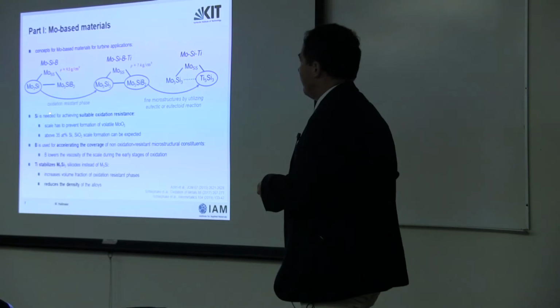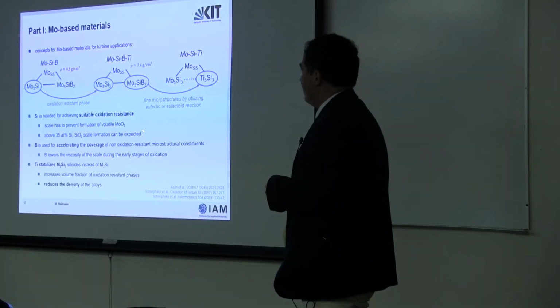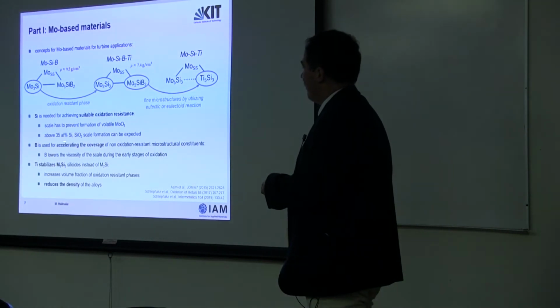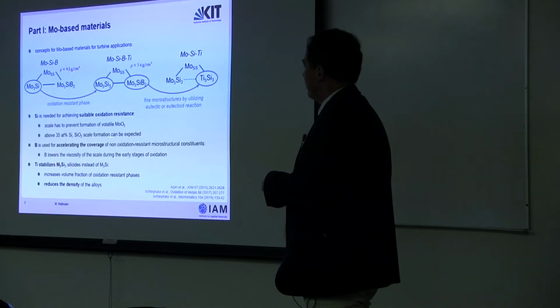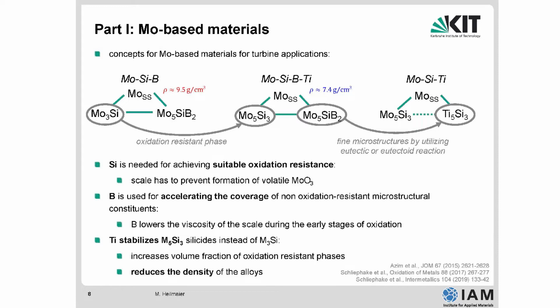You need silicon to avoid this, but you need a high amount of silicon, above 35 atomic % silicon, to get a silica scale formation here, which is a lot. Yeah? So we try to avoid this because this material becomes extremely brittle. What else could you do? You could add other elements to alleviate the fact that you need high silicon contents.